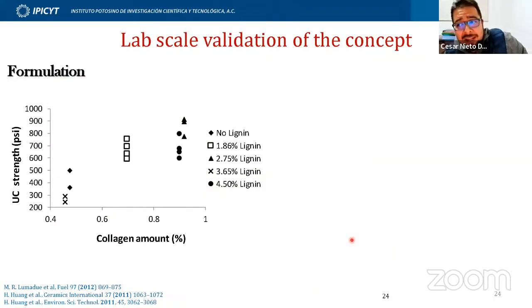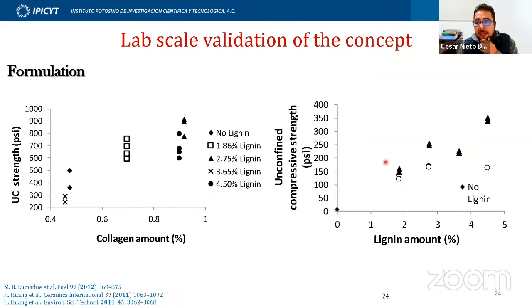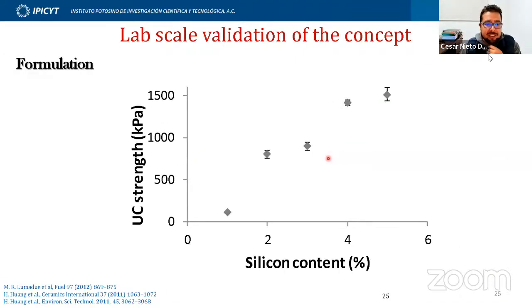First, at lab scale, we validated the concept by exploring the formulation. We saw that when we use a different amount of collagen, the UC strength, which is the strength of the briquette dried at room temperature, increases when you increase the amount of collagen. Also, it makes an interaction with the lignin that we are using. We also explored the effect of lignin: if we increase the amount of lignin, we increase the strength of the briquette. And if we increase the amount of silicon metal in the formulation of the briquette, we also increase the strength.